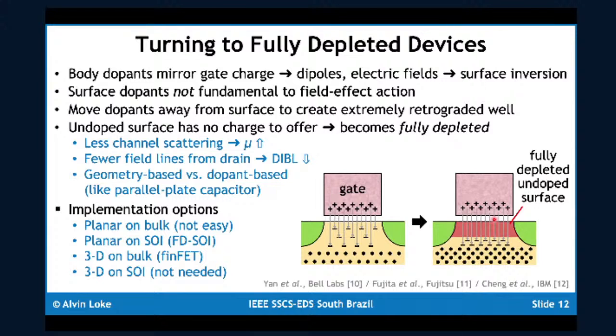Now, there are multiple implementations of a fully depleted device. You can build a planar on bulk, although this is very difficult to do because growing an epitaxial layer of undoped surface requires high temperature, which results in a lot of outdoping from the heavily doped region underneath.